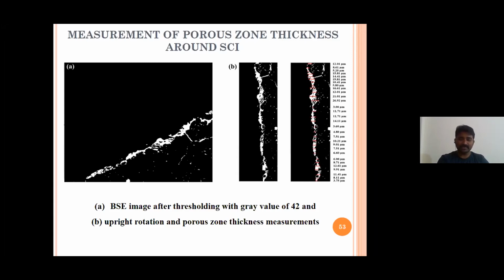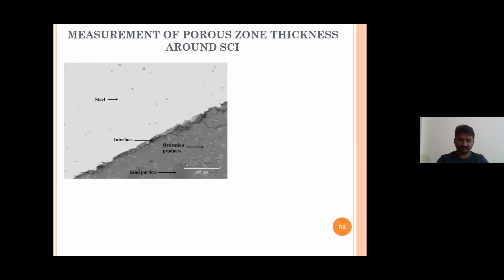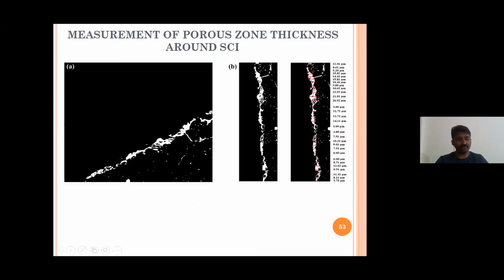As we are doing images, we have to be very particular about the magnification that we are using. All the SEM images were taken at a fixed magnification of 500x, and the grayscale thresholding value was 42. As you can see here, this is 12.1 micrometers, 8 micrometers, 5. Likewise, at each location, the red marks you are seeing are the selected values, and you will come up with these values through the image analysis tool, ImageJ. All this is image processing. I'm not discussing how I did this, but we did this using the image analysis tool.